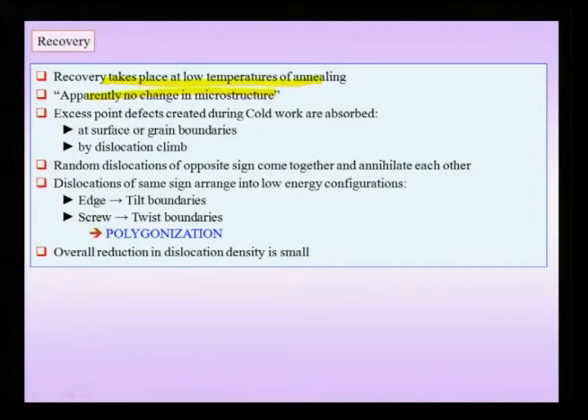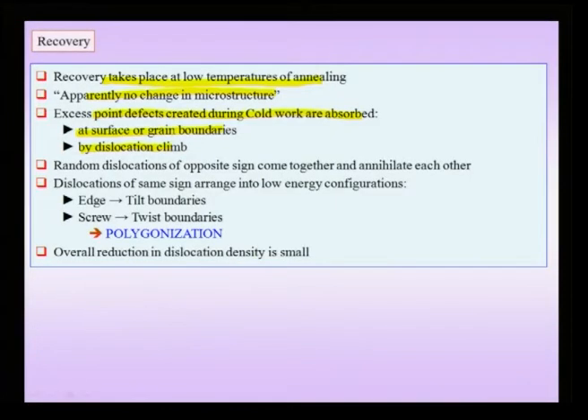And this is because the excess point defects created during cold work are absorbed at surfaces and grain boundaries, and also by dislocation climb. And as you know, it is not possible to observe vacancies or clusters of vacancies using an optical or scanning electron microscope. Even in a transmission electron microscope, it is actually difficult to observe vacancies, and you have to use some indirect methods to find evidence for the presence of vacancies. Now, of course, certain vacancy clusters can be located in a transmission electron microscope. So, during recovery, there is a pronounced decrease in the excess point defect density, and for instance, vacancies which are created during cold working are absorbed at grain boundaries or surfaces, and even by dislocation climb, the vacancy concentration decreases.